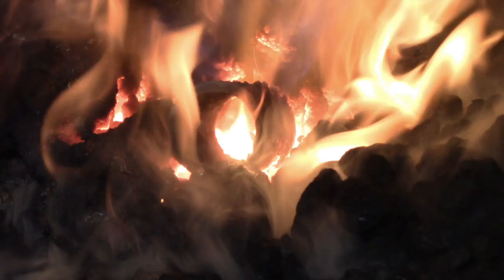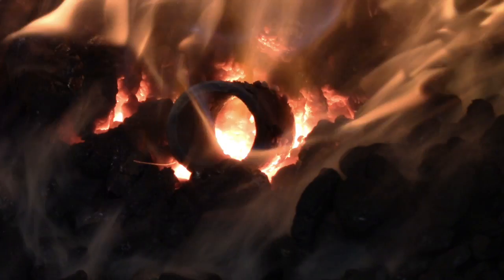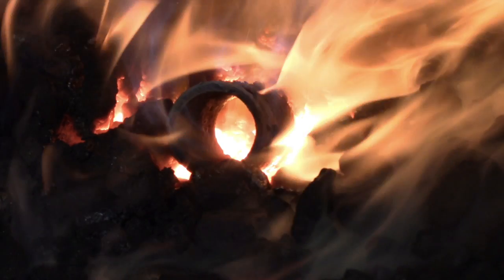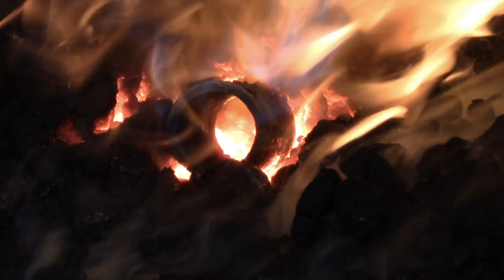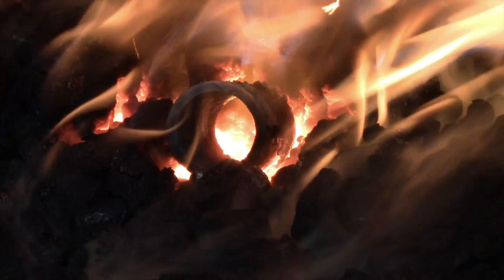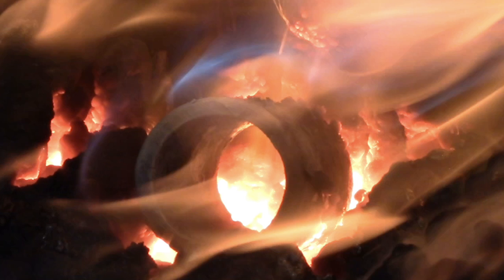When they reach a critical level your body starts shutting down, and at this point there isn't any way of reversing that process once it starts. If you look at the top rim of this pipe you're going to see a white frosty coating starting to develop. That's a result of the galvanized coating starting to break down and the zinc is migrating to the surface.